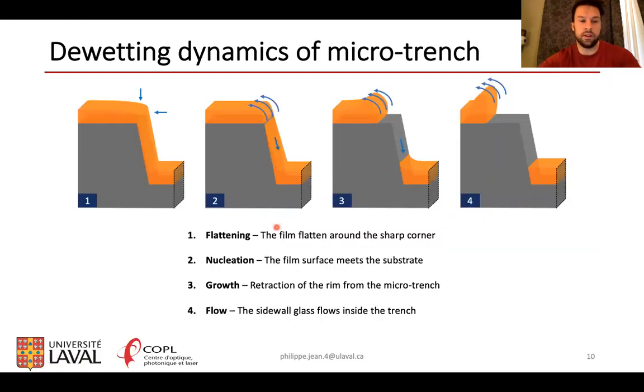So what's really interesting for us is actually the dewetting dynamics around a microtrench. So everything starts from this sharp corner here, and as you heat the glass, the film will tend to flatten, and this will lead to a thinning of material around the edge. And at some point, this will cause the formation of a hole, and this hole will then grow through the combination of a rim retraction. So the rim will actually expand by self-diffusion away from the trench, and the glass that was on the sidewall will flow inside the microtrench, leaving a very flat and very nice strip waveguide.